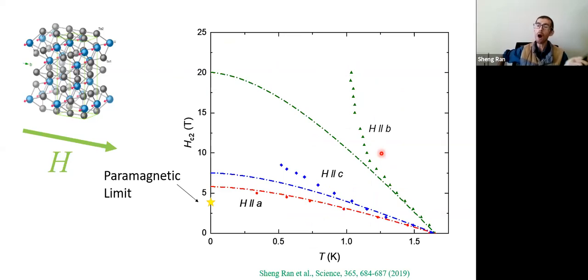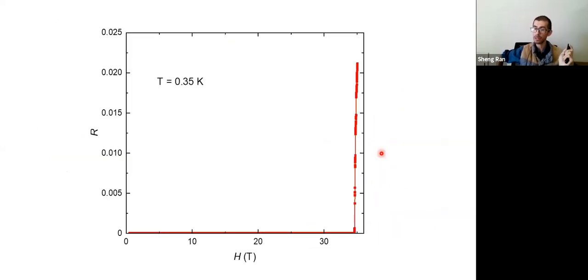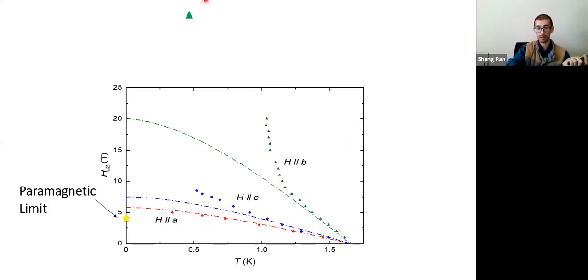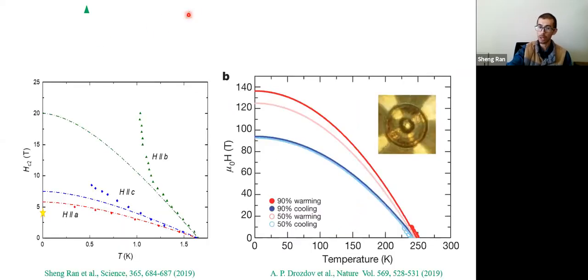So in order to know how high the critical field really is, we took the sample and did an experiment at the National High Magnetic Field Lab. Here I'm showing the resistance as a function of magnetic field. We can see it's all the way 0 up to 35 Tesla. And then all of a sudden there's a wall, and it goes to the normal state. So the critical field at 0.35 K is 35 Tesla. If we plot on the same plot, 35 Tesla is here. To give you a comparison,